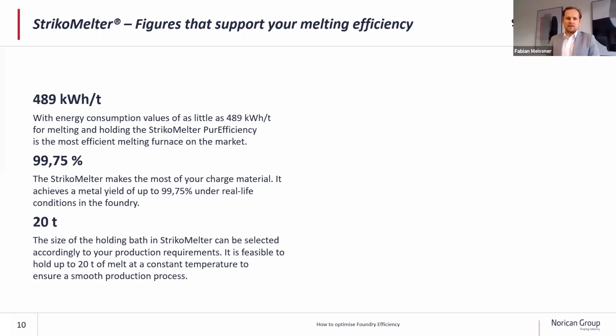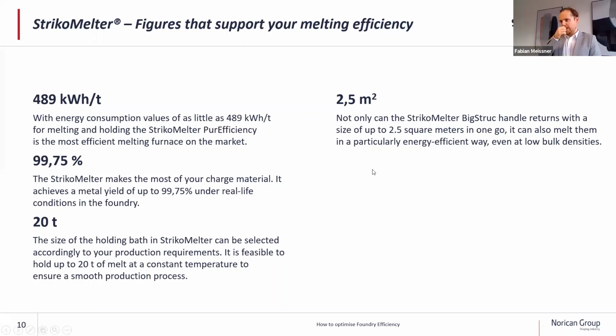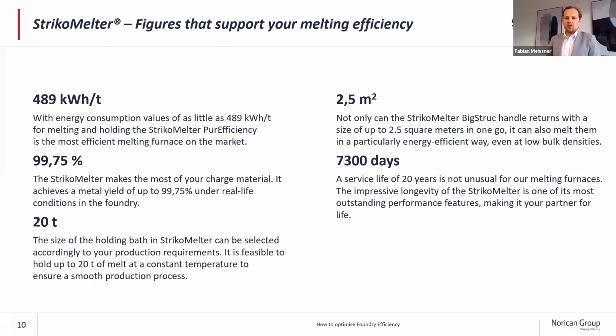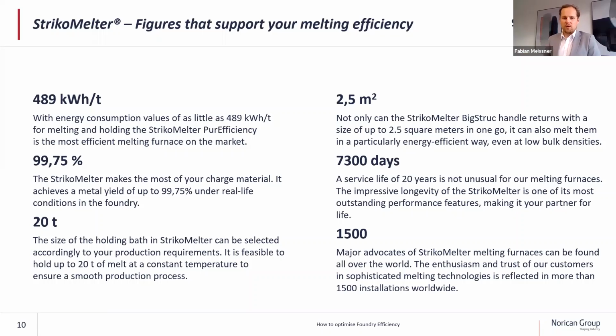We build furnaces with a holding bath size of up to 20 tons. We can melt parts of up to 2.5 square meter size in our shaft. We can even make the shaft bigger. So, for example, when you're working now with structural parts, this could be an interesting solution for you. As mentioned, our furnaces are very long lasting, and a service life of 20 years is not unusual. And we have more than 1,500 shaft melting furnaces, Striko melter model, in the field. This has always helped us to further improve and optimize our system.